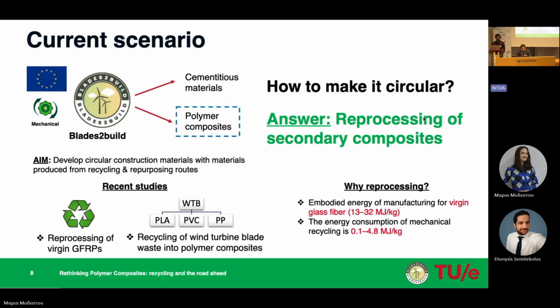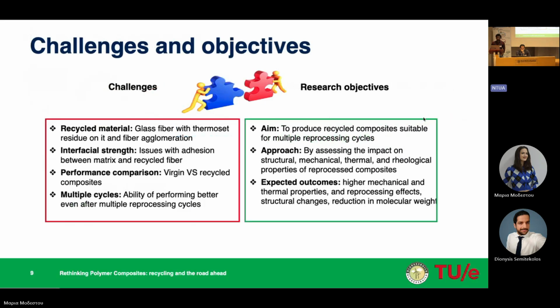For example, the energy consumed for mechanical recycling would be somewhere around 0.1 to 4.8 megajoules per kilogram. So keeping all these in mind, we also need to think about certain challenges which we come across during this research. For example, there is a huge challenge with the material itself. As I said earlier, these composite materials are made up of glass fiber and thermoset resin. So when we start shredding these materials, we end up having glass fibers with thermoset residue on them, which is also quite a challenge to process in secondary composites.